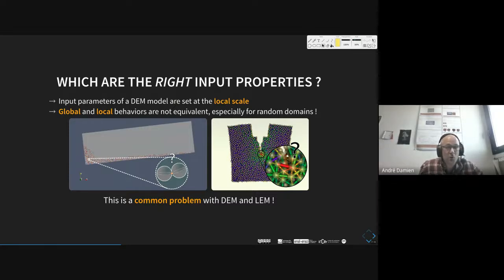In fact, we don't know what to put inside the contact law, to get the right value of this contact law. We have to solve some inverse problems, and we have to involve a lot of experiments, observe the experimental results, try some local properties, and make a kind of iteration to converge towards the right solution. So it's not so comfortable for users. And this problem, I think, is a very common problem with DEM and the lattice element method.